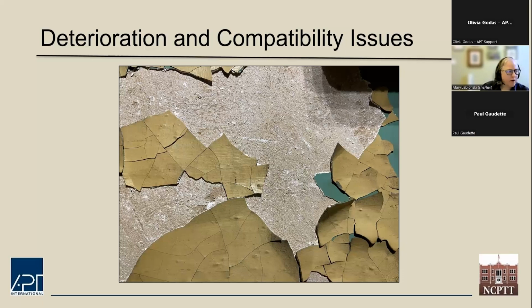As new paint layers are added over old, the paint coating becomes quite thick. With the newer paint types that began to be used in the 30s, the paint will not penetrate the cracks well. These cracks remain. The newer paint films and varnishes are stronger than the older ones, and as the paint and varnish age, it shrank more than the distemper and oil paints below. These stresses lead to cracking and peeling of the paint coating, which begins at the old cracks. Increased shrinkage of the outer finish layers forces the paint film to curl away at the cracks. On some areas of walls, the paint has adhered so well to the finished plaster coat that the peeling paint coat is taking the finished plaster with it, as you can see in this image.